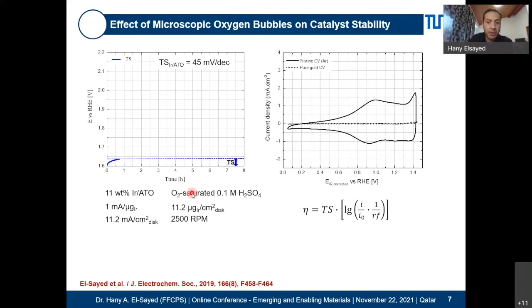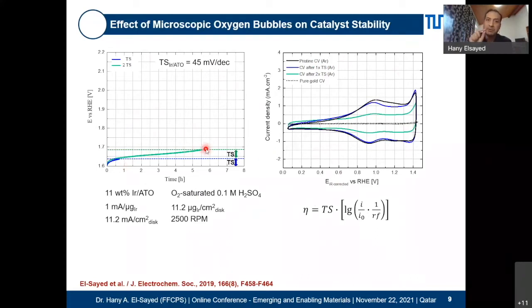But the interesting part is we stopped the experiment, we purged the system with argon, now there's no oxygen, and you find out that the CV is almost identical, and we did not really lose anything. And we continued. We went to the second Tafel slope, and as you can see here, with the second Tafel slope, we should have only 1% of the catalyst remaining. And in reality, we have about 50%. And you keep going all the way up to the jump.